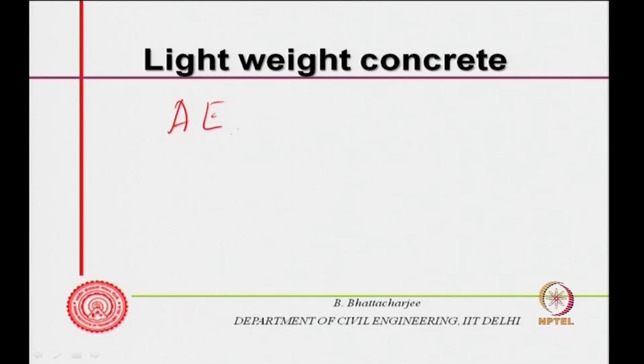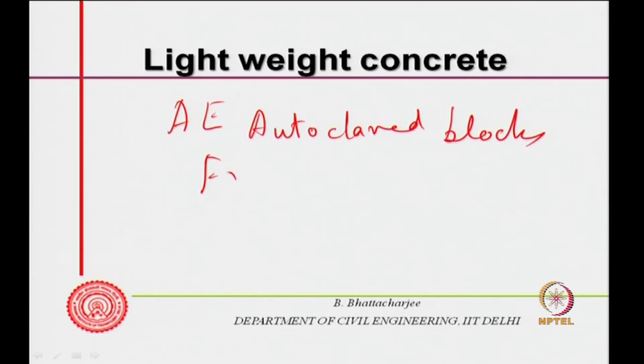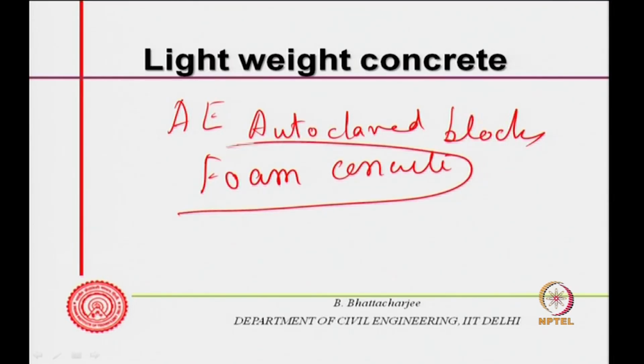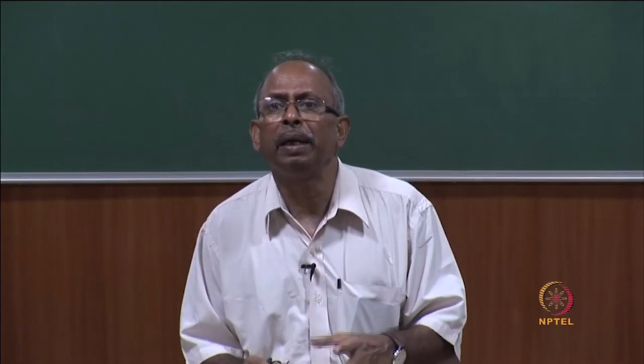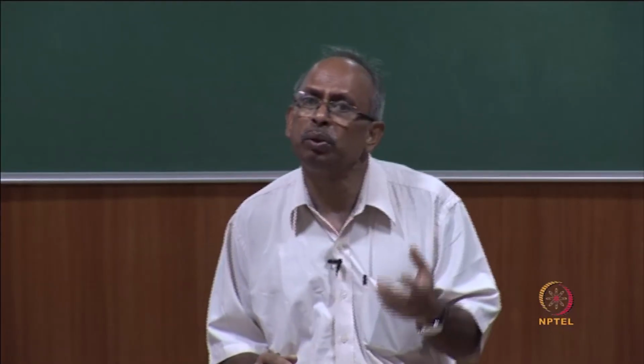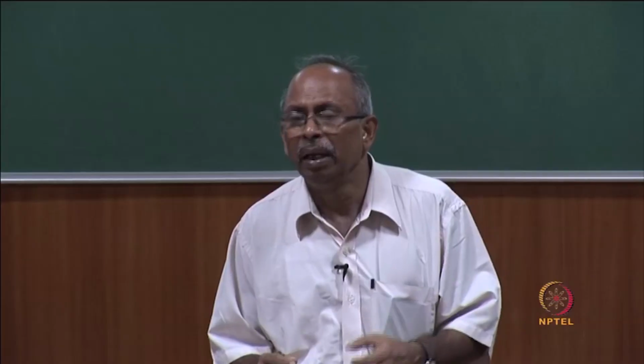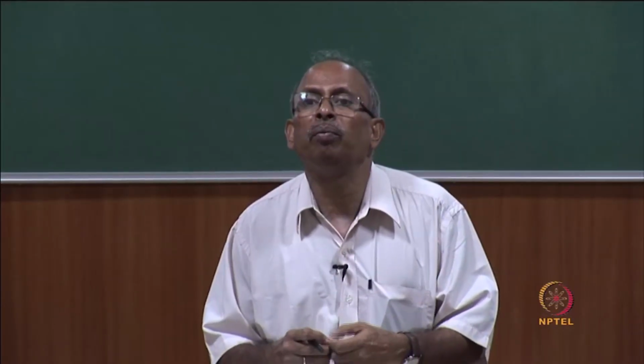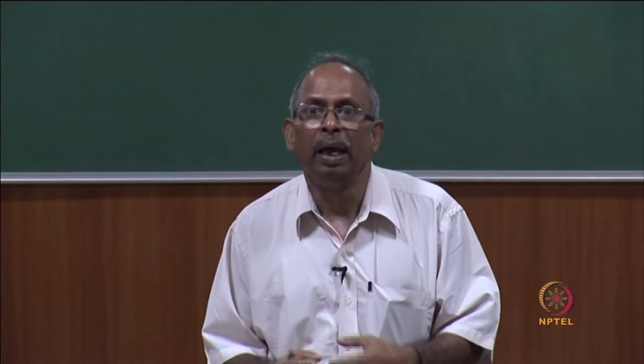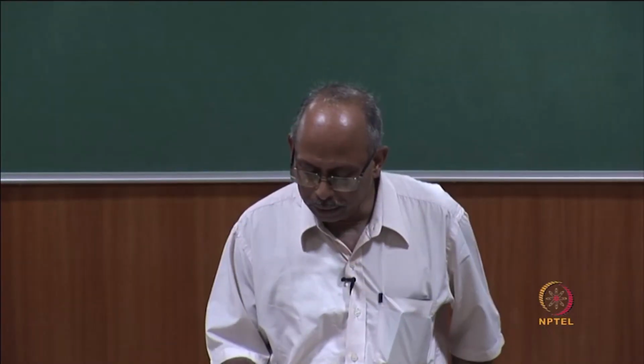autoclaved blocks, foam concrete. Now, you have some sort of foaming agent, aluminum powder, or even organic foaming agents these days. So, you make foam and put it into the concrete or mortar that you make, and you can make foam concrete. There are some agents which you can add in the concrete right in the beginning. They will go into the concrete system and generate a lot of foam or void system gases, and these entrapped gases can give you aerated concrete.